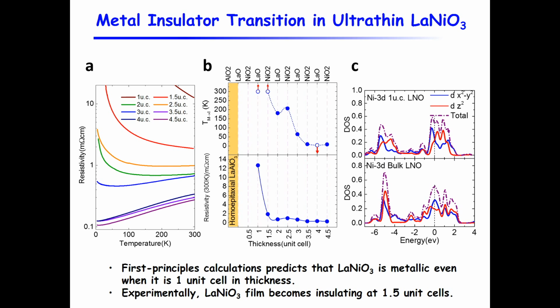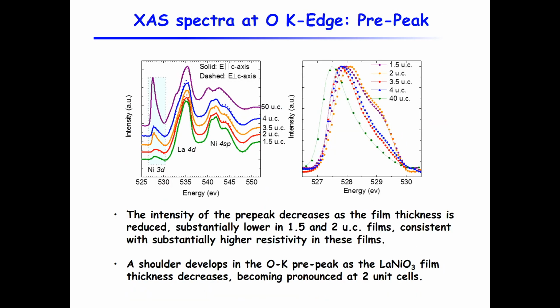And I think the Cornell group reported the 2 unit cell. And when I presented there, they were speculating that it's probably because we used the lanthanum aluminate buffer layer that they did not. That, of course, provides as perfect as possible a buffer layer for the growth of the layer on top of it. What I try to say with these first principle calculations is that the first principle seems to suggest that in these materials, grown under this kind of strain, even 1 unit cell should still be kind of conducting. It's less conducting than bulk, but it should still be conducting. Yet we do observe that it becomes insulating below 1.5 unit cell.